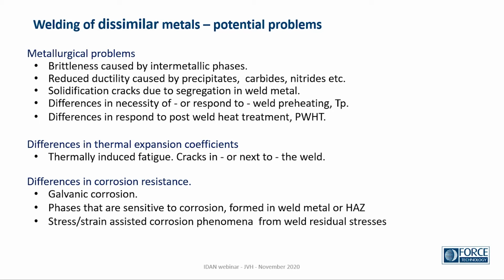And we might have solidification cracks due to segregation in the weld metal, and differences in the necessity of, or response to, weld preheating. I mean, one material would need preheating, and another one would definitely suffer from too much preheating. And if we try to combine them, we need to find a compromise. And the same goes for post-weld heat treatment. Some metals would need it, and others would suffer poor properties after the same heat treatment.